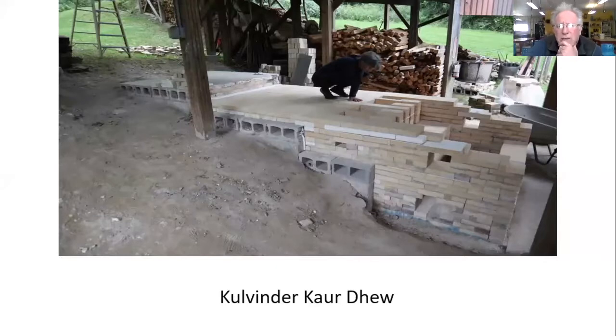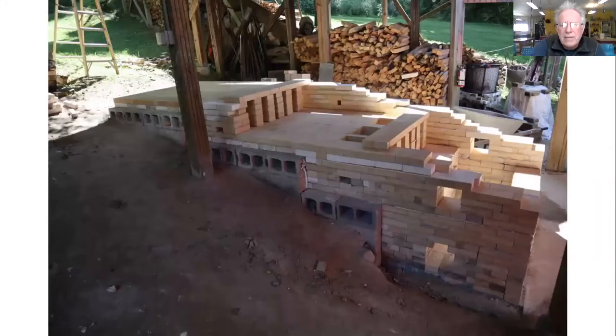We also introduced clean outs in each of the fireboxes. And this is Kulvinder, who did the documenting. And I think in that picture, Kulvinder is contemplating or meditating on a little central wall that we introduced in this design that goes the entire length of the kiln as part of that tie-in. So instead of having five grate bars, we went with three grate bars instead, with one of those grate bars being this central wall. And I have a photograph of that.